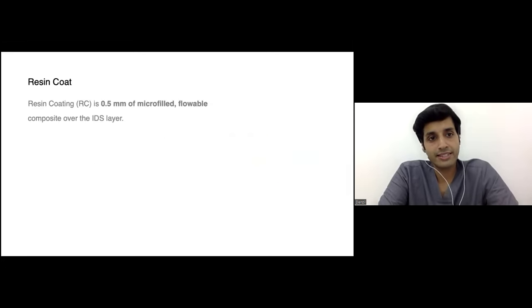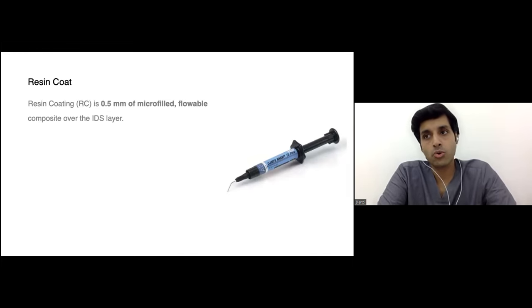Resin coat is again similar to what the name suggests. It is nothing but a resin. It is usually a flowable composite, a microfilled one to be more specific. It's about 0.5 millimeters of the resin coat, a flowable placed over the adhesive. So the adhesive forms something called the hybrid layer. Above this hybrid layer, to make it slightly thicker and stronger, we use the resin coat. So what does the resin coat do?